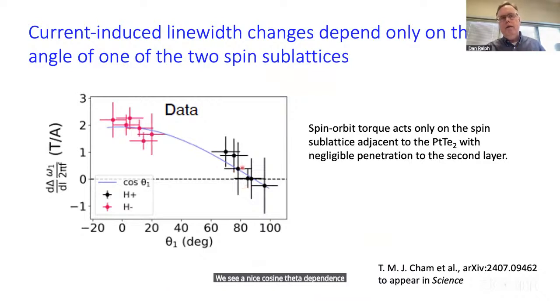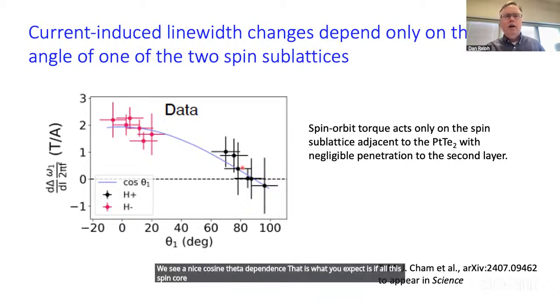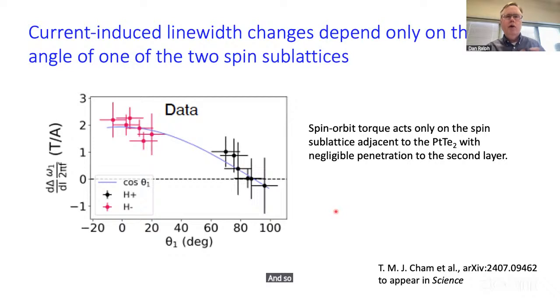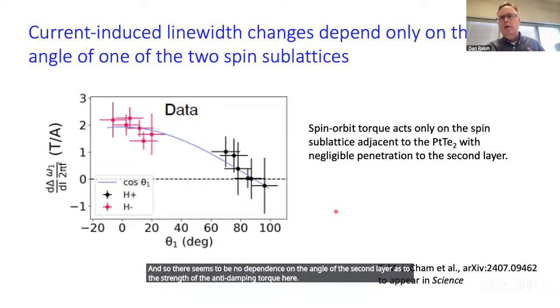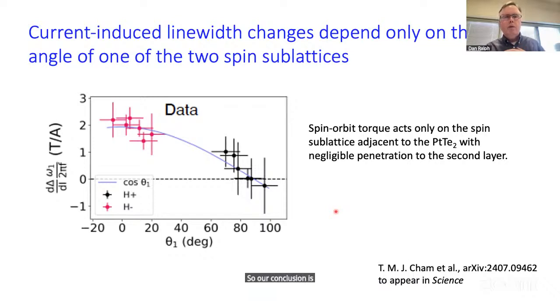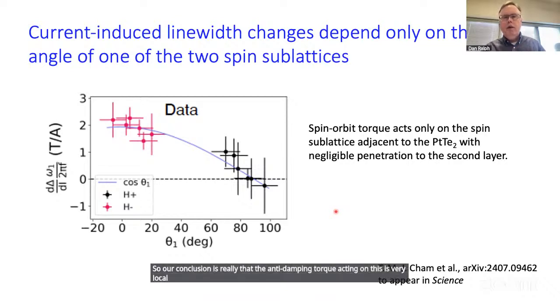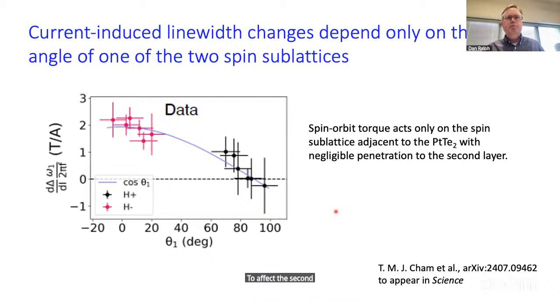expect if all the spin torque is acting on just that first spin sublattice and not the spin sublattice in the second layer. And so with this, there seems to be no dependence on the angle of the second layer as to the strength of the anti-damping torque here. So our conclusion is really that the anti-damping torque acting on this antiferromagnet is very local, acting only significantly on one spin sublattice and not penetrating through to the second layer to affect the second spin sublattice.